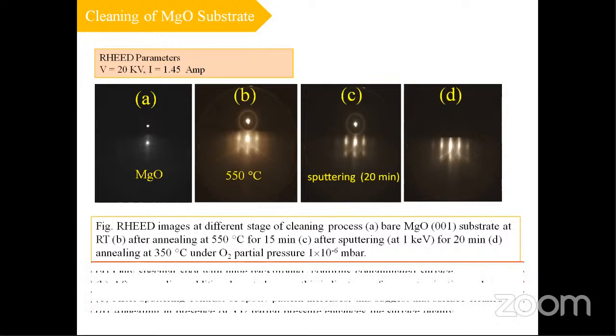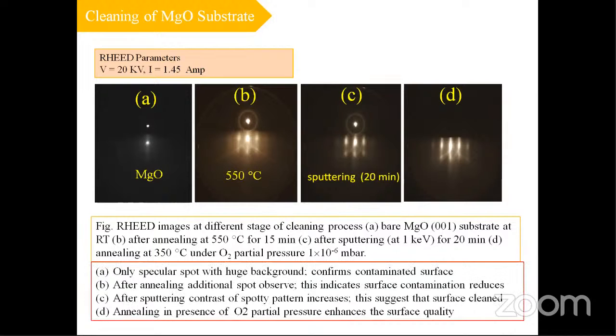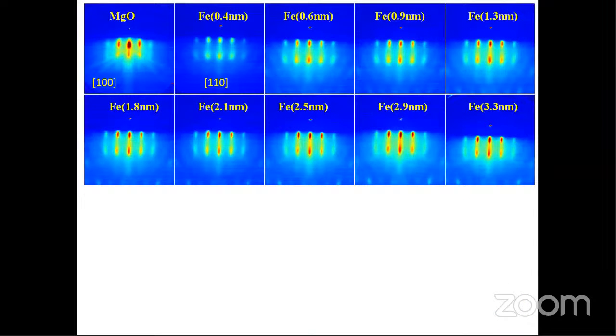Now, after cleaning, we started the deposition of Fe on the cleaned MgO substrate. First, when the thickness of Fe is very low, we observed a broad spotty-like pattern, which confirms that the growth nature of the Fe film is epitaxial, but at a very low thickness, the film is in island form.